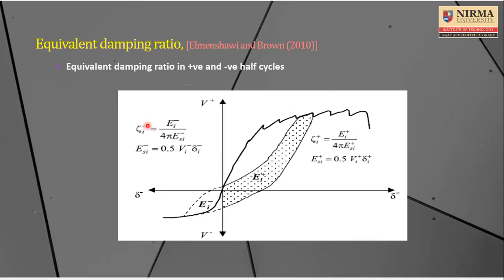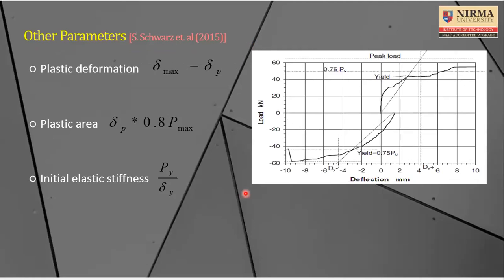And as I said, many researchers have their own reservation, so they have carried out a lot of research based on the forward cycle as well as the backward cycle, which is generally unsymmetrical. There is very good research by Elmenshawi and Brown in 2010, where they separated the positive cycle and negative cycle independently and tried to figure out if there is any difference in the equivalent damping ratio. Their study suggests that there is not much difference in the equivalent damping ratio, but it is always unsymmetrical.